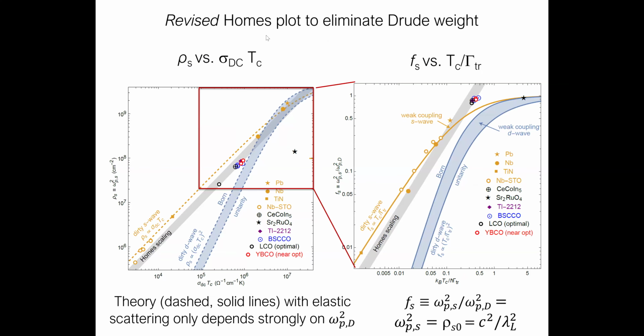So we went back to the Homes plot, and we put these calculations that I just showed you for the scaling of the superfluid density with the transition temperature due to disorder alone. These are the Homes variables, superfluid density versus sigma dc times Tc. And you see that the Homes scaling line, that's this gray bar, basically accounts for the data plotted here, with the exception of strontium ruthenate, which we added to the graph, which is way over here, has nothing to do with the Homes scaling. But also there are no data points on our dirty D-wave curve. So what happened there?